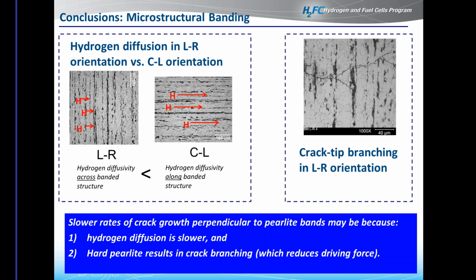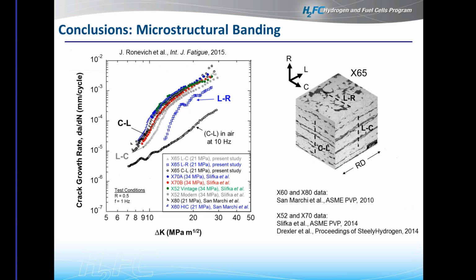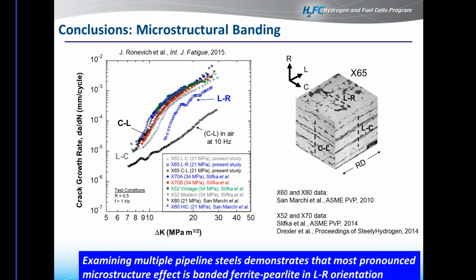And so when we compare the results of this banding microstructural study to a whole bunch of pipelines that have now been examined in the literature, essentially between us at Sandia and NIST, what we see is that despite the difference in microstructure, which we'll see between all the different pipeline grades from X52 to X70 to X80, those all tend to fall in this narrow band of fatigue crack growth rates. And really the outlier is this LR orientation. This gives us a little bit more insight that the microstructure really is playing a role. It's not necessarily related directly to strength, because X80 steel is going to be much stronger than an X52, but really we need to be paying attention to what the microstructure is doing.